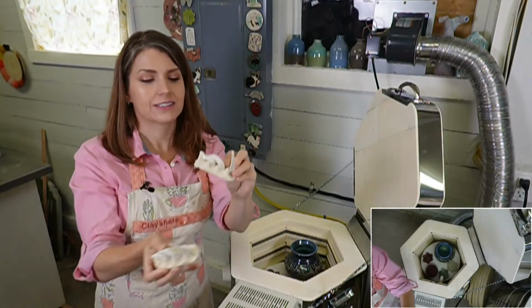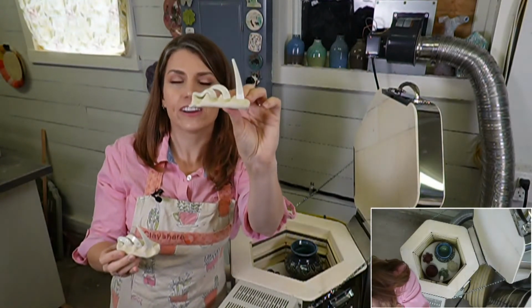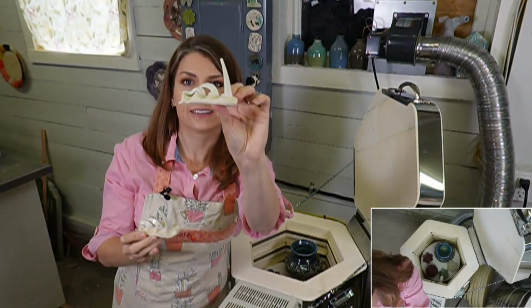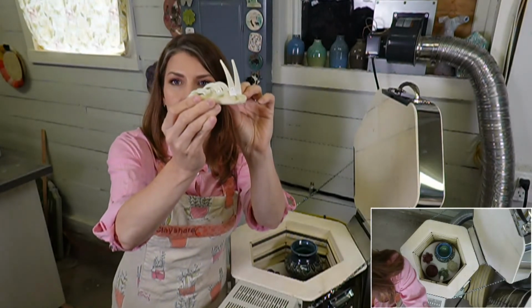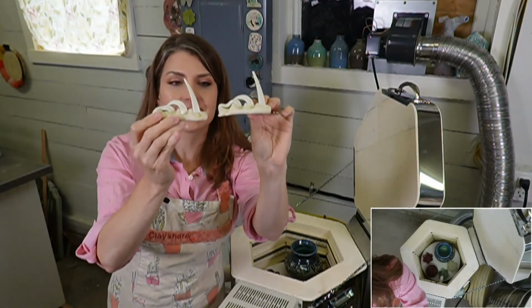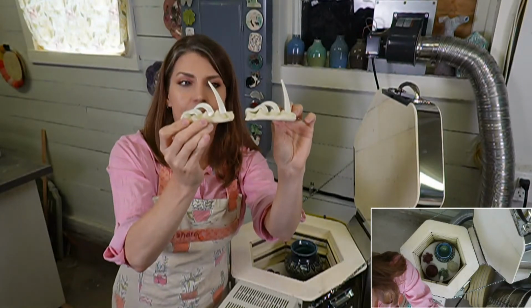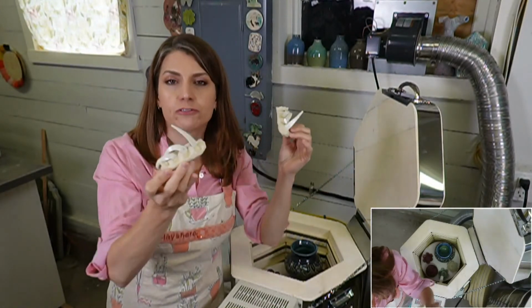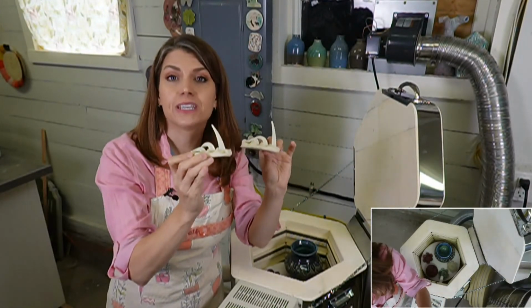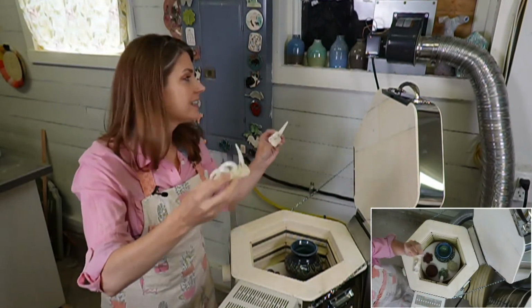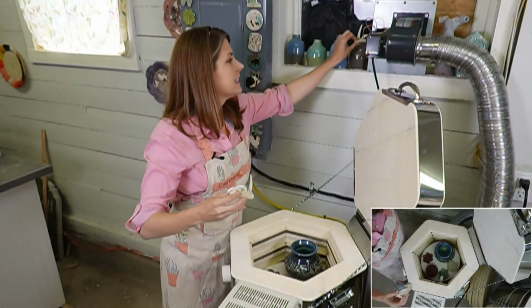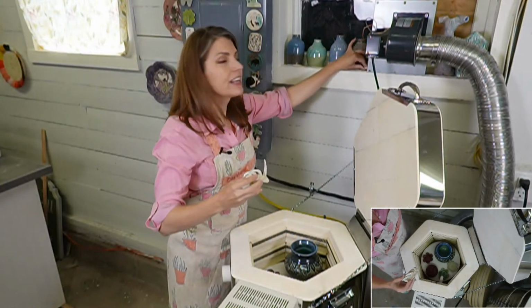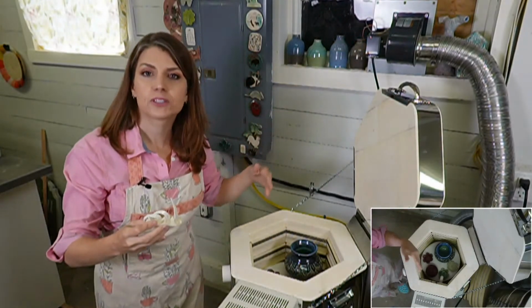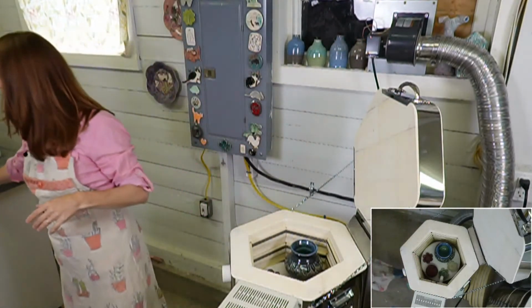So this was from the firing I did on Tuesday. And this is today's firing. So we can compare 2 firings and see how consistent they are. Completely even, which is normal when you first get a kiln. When they're brand new, they should be even for a long time. As they get older, you will start to see your kiln running a little cooler, and that's normal as the elements wear down. So that's a completely normal thing to have happen.